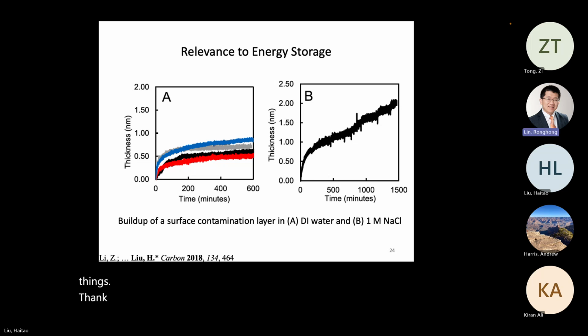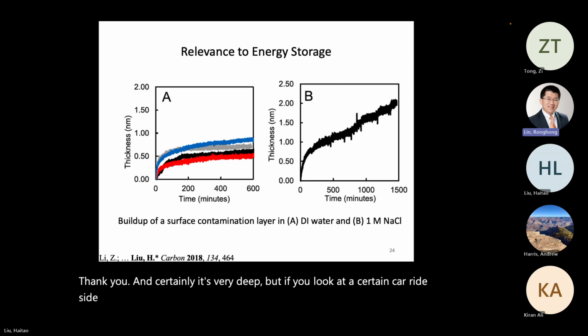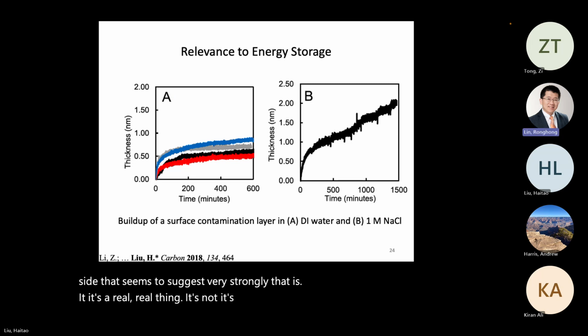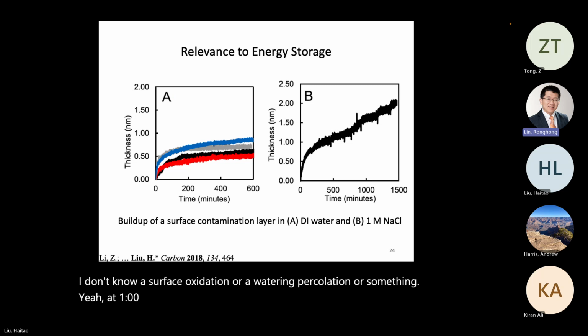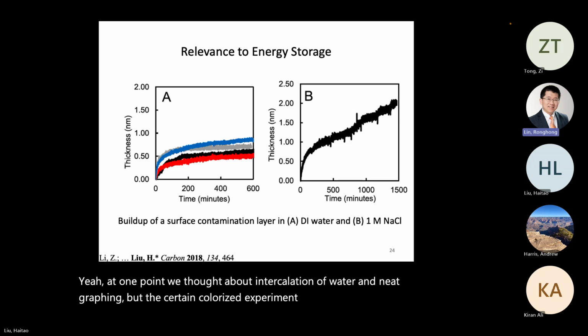And certainly it's very deep, but if you look at the sodium chloride side, that seems to suggest very strongly that it's a real thing. It's not, for example, a surface oxidation or water intercalation or something. Yeah, at one point we thought about intercalation of water underneath graphene, but the sodium chloride experiment showed that's probably not the case.